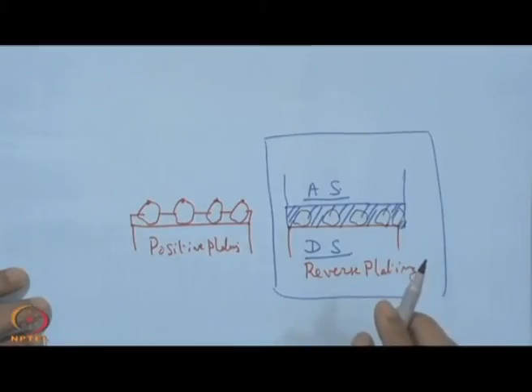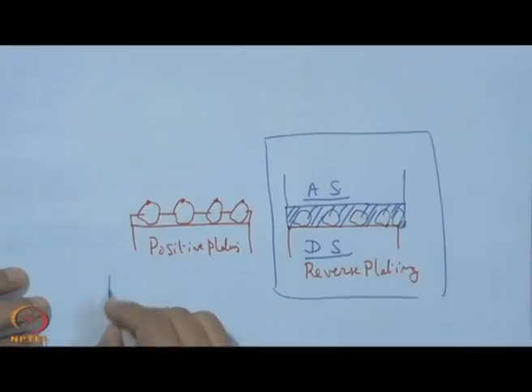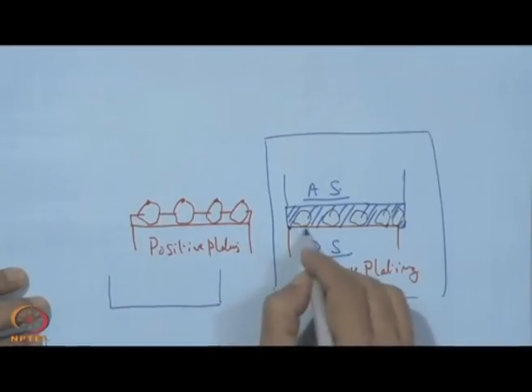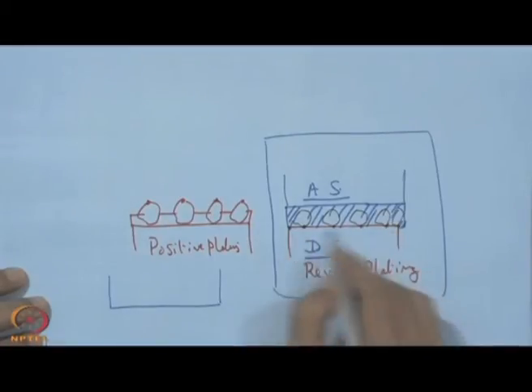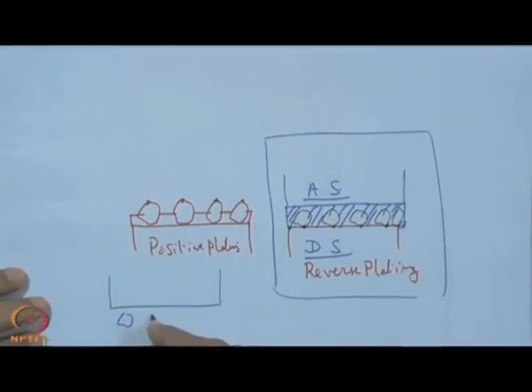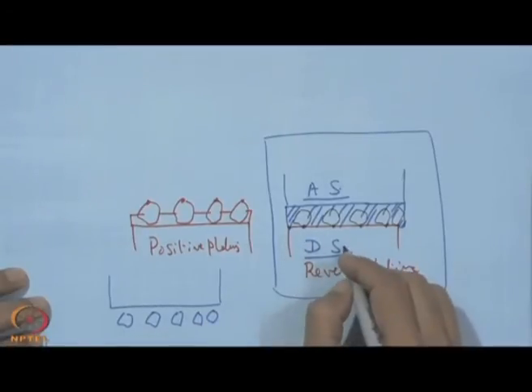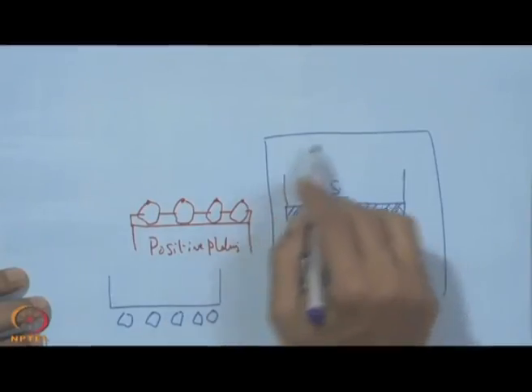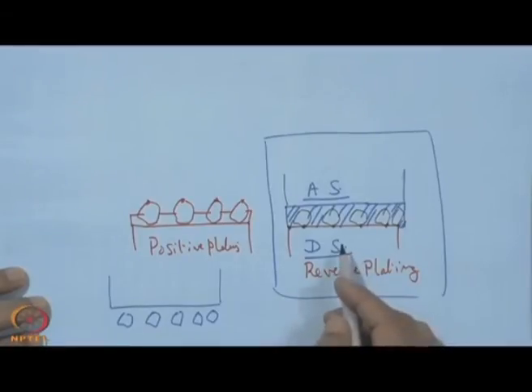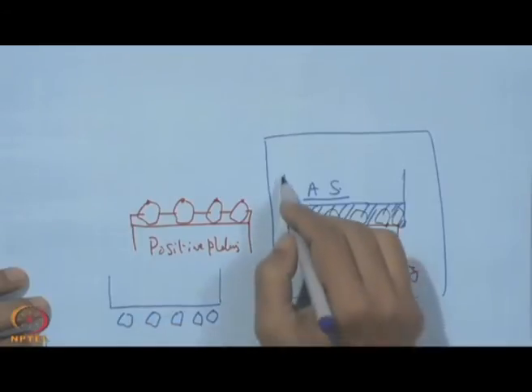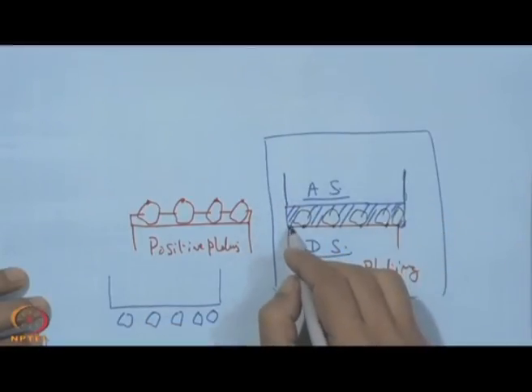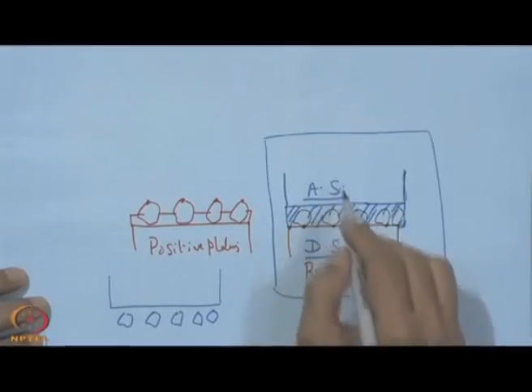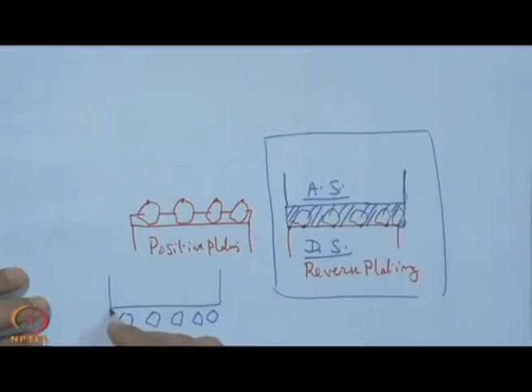Now, after that this dummy substrate will be chemically etched, so that we get a substrate surface where each point is now on this surface and they are at the same height. So, in this case we get this abrasive layer, which at the very beginning was resting on this dummy substrate, but after that the bonding is carried out by initiating this electrochemical deposition, and this electrochemical deposition was continued. So, it could cover the entire space between the actual substrate and the dummy substrate. So, now the situation is something like this. So, this is the coverage.